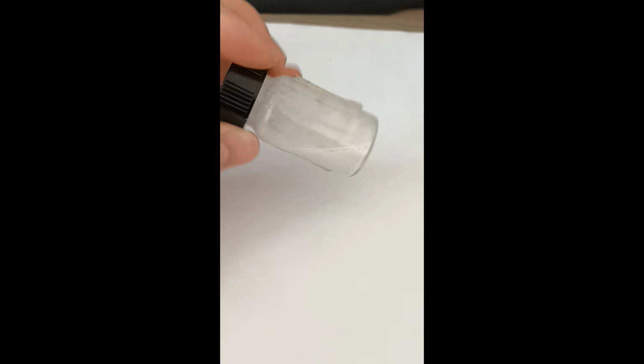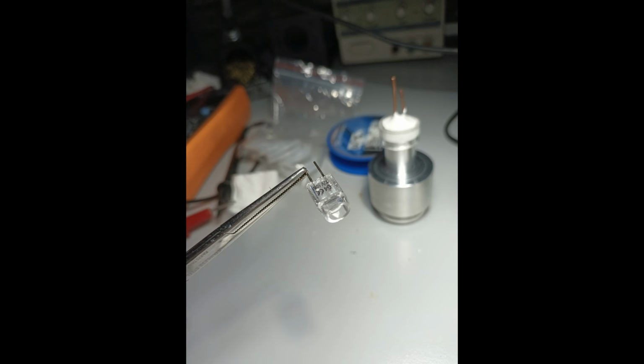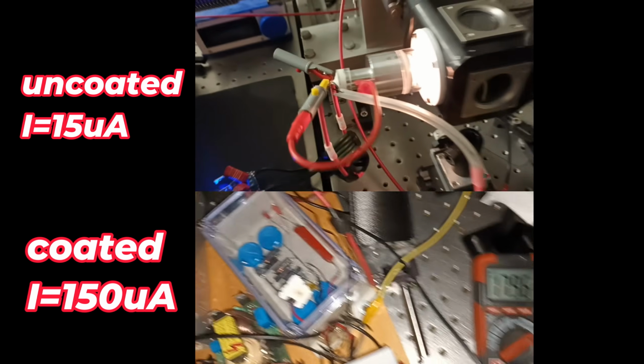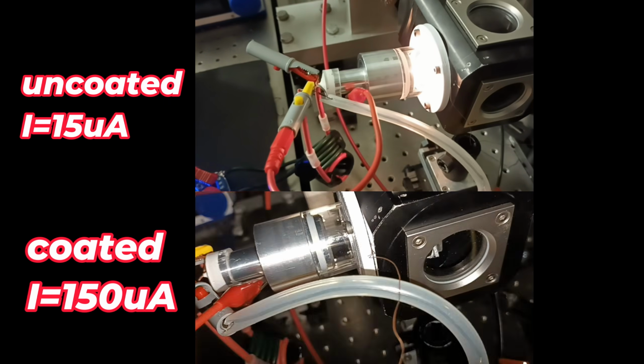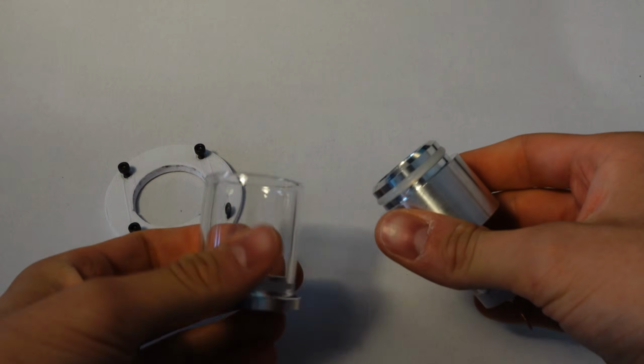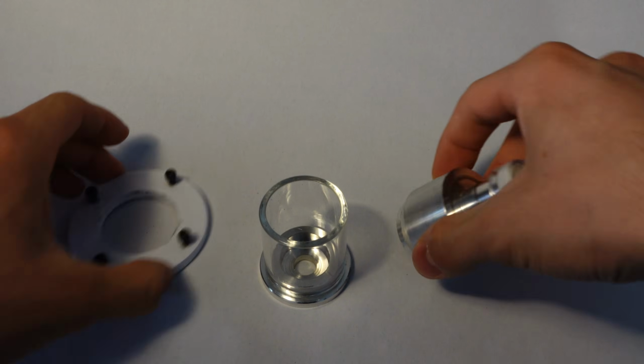This wet liquid, consisting of barium and strontium carbonate, when cast over the filament and dried, will make a very low work function material. This way we are gonna have much more electrons at much lower temperature. You can clearly see the difference it makes between a non-coated filament and one that is instead coated, both in current and in light background.